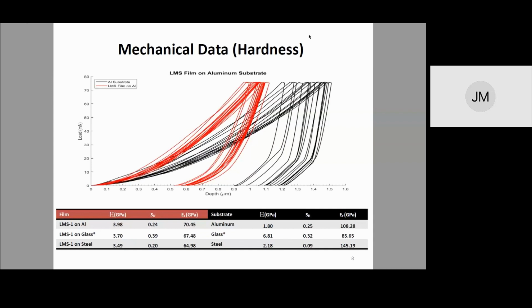You can see in the left table the hardness values for the films across the three substrates were relatively similar, which means that the tests that we conducted were indicative of the ceramic film itself and did not depend on the substrate beneath. Steel and aluminum were both approximately double the hardness on the film than the substrate, and glass was about half, which was to be expected as silicate glasses are harder than metals.